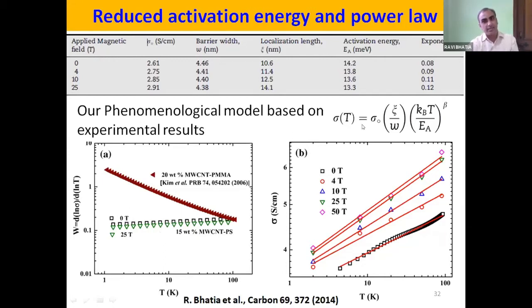For explaining this data, we needed to propose a phenomenological model ourselves, that this power law behavior should have a delocalization and a localization length and barrier width. I will not go into the details, but explain that with the application of magnetic field of 4, 10, and 25 Tesla, the localization length is increasing, which indicates that this field is capable of delocalizing the charge carriers in a sample of 15 weight percent MWCNT polystyrene composite. So these two things are very important, that there is a correlation between localization length and the magnetic field.